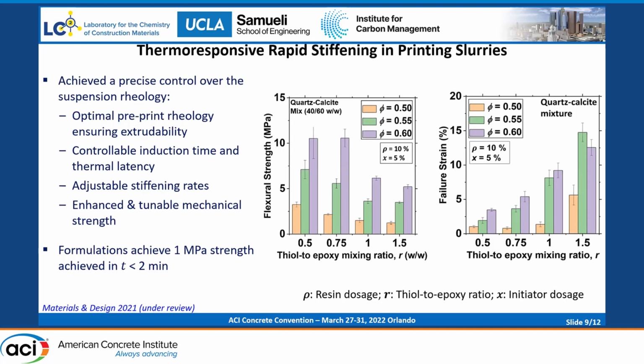By using more and more solid content, we'll be able to improve the flexural strength of the suspension. That is obvious. What is interesting here is the effect of this epoxy to thiol mixing ratio. By using a mixture with excess epoxy, we'll get a higher mechanical strength, but we need to compromise on the strain capacity of these suspension composites. But if we have a more or less stoichiometric ratio of epoxy and thiol, we may be compromising on the flexural strength, but we get a good strain capacity.